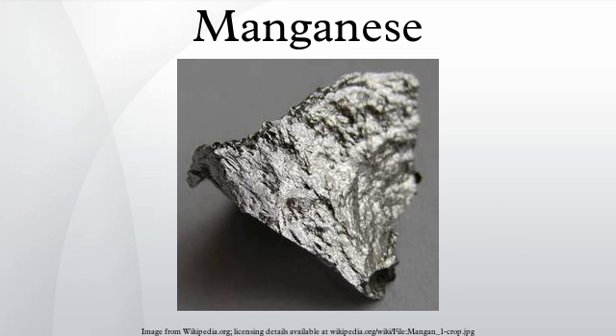Aluminium alloys. The second large application for manganese is as an alloying agent for aluminium. Aluminium with a manganese content of roughly 1.5% has an increased resistance against corrosion due to the formation of grains absorbing impurities which would lead to galvanic corrosion. The corrosion-resistant aluminium alloys 3004 and 3104 with a manganese content of 0.8 to 1.5% are the alloys used for most of the beverage cans. Before the year 2000, more than 1.6 million tons of those alloys had been used. With a content of 1% manganese, this amount would need 16,000 tons of manganese.